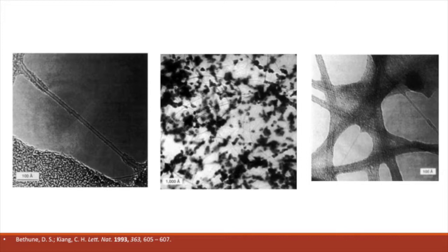However, upon TEM analysis, he observed that his product was primarily single-walled carbon nanotubes with diameters of roughly 1.2 nanometers, as shown in the first figure on the left. The round spheres that can be seen sticking to the sides of the carbon nanotube were determined to have diameters that correspond to fullerenes that range between 60 to 100 carbons. This showed that although single-walled carbon nanotubes could be produced, they could not be purified and collected.